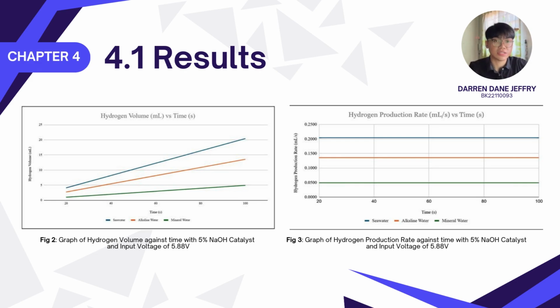Hydroxide ions also increase the conductivity of the electrolyte, so this also supports why alkaline water is faster than mineral drinking water. Mineral drinking water has struggled due to its low ionic conductivity. It starts at 1 milliliter and reaches only 7 milliliters at 100 seconds. Even with the sodium hydroxide catalyst added to all 3 of these electrolytes, its performance for the mineral drinking water is still limited.